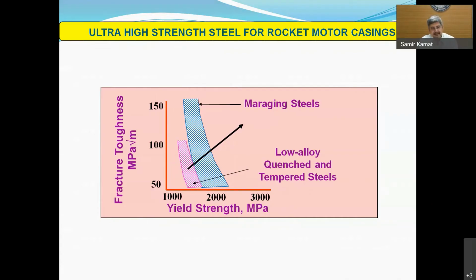So in DMRL, in the late 80s, there was a thinking. One of the limitations of Maraging steel is the cost, because it has more than 30% alloying additions and expensive alloying additions like nickel, cobalt. So there was a thinking in DMRL that whether we can make a low alloy steel, and by low alloy, I mean alloy content less than 8%. Is it possible to design a low alloy steel which has comparable properties to Maraging steel, and where you can do quenching by air cooling? So it has sufficient hardenability that you can get martensite just by air cooling, not by quenching in water or oil.